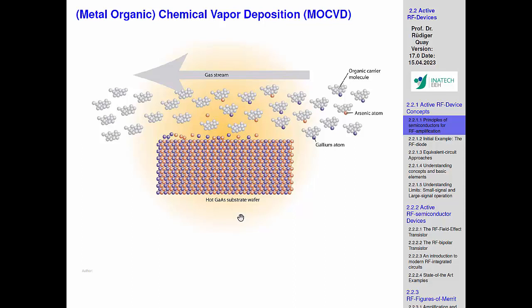then it wouldn't be a good technique. And this MOCVD here, this chemical vapor deposition, has a growth rate in the range of 1 micrometer per hour, which is already good. And for LEDs, for example, you need a couple of microns to do something useful. Same for electronics. So within reasonable time, you can produce good surfaces. You can produce a growth rate which gives you a device. And through this very nice design of the reactors, you can actually get a decent homogeneity. And you saw the wafer spinning, and there's still some dependence over the wafer of the thicknesses and also the dopings, but it's reasonable. So it's predictable and useful.